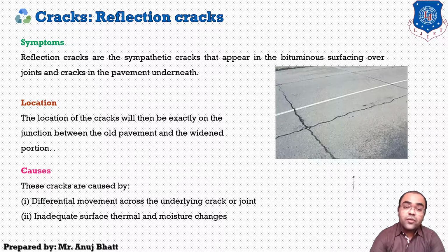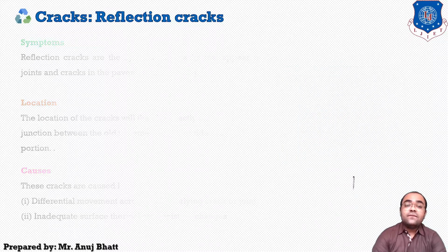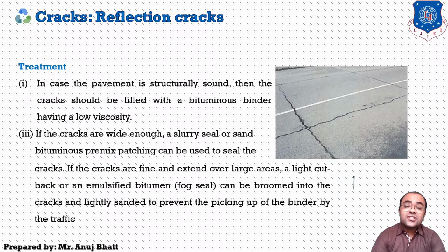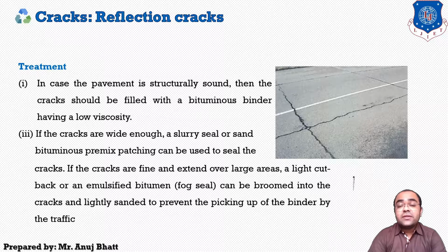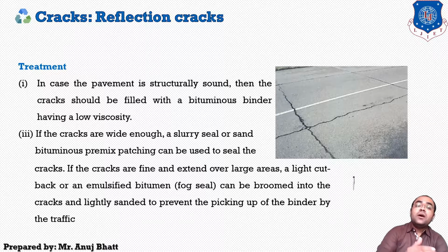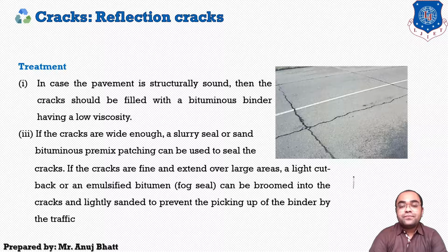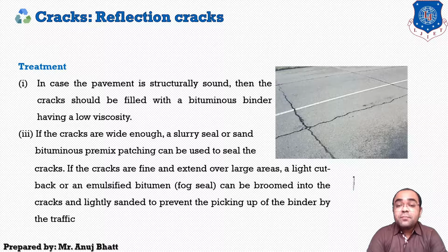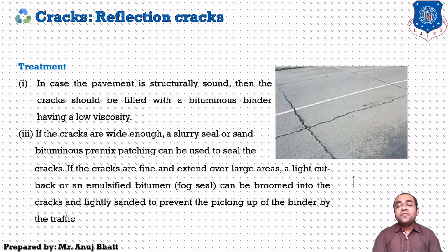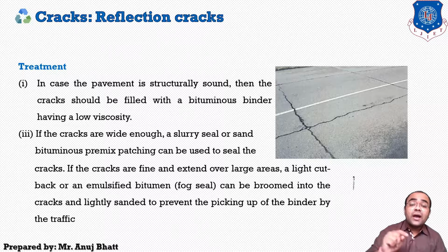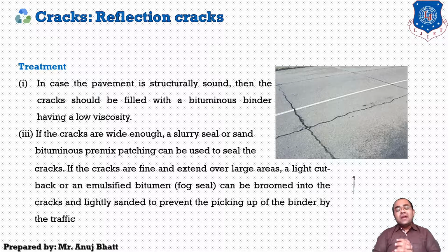If we talk about the treatment, then for reflection cracks, the treatment would depend on whether the pavement is structurally sound or has become distorted or unsound. In case the pavement is structurally sound, then the cracks should be filled with a bituminous binder of low viscosity so that it can be poured and worked into those cracks.